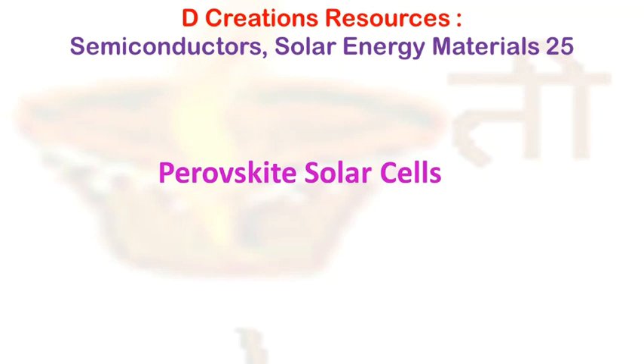Now a perovskite film is typically processed by either vacuum or solution method. So film quality is very important. Typically the active layer of a perovskite solar cell is deposited via either a 1 or 2 step process. In the 1 step process, a precursor solution, which could be a mix of CH3NH3I and PbI2, is coated, that then converts to the perovskite film upon heating.